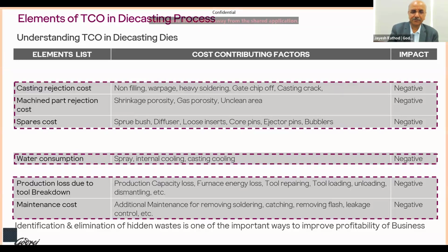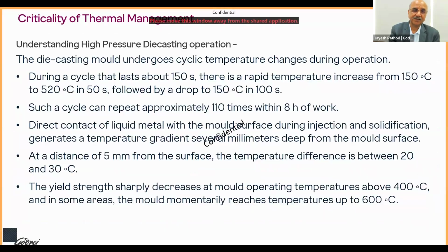So if we go into detail one by one, that indicates that mainly it is because of thermal management that casting rejection occurs. I think the casting rejection occurs, as informed by Joe through some study by NADCA, because porosity is the major cause of rejection. And again, porosity is influenced by your thermal management, besides many other things. But thermal management has a very important influence on the rejection of the castings.